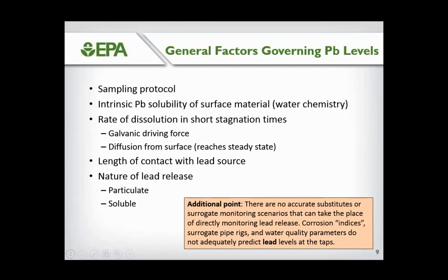So things like the galvanic driving force or the rate of diffusion from the surface are critical. The length of contact with the lead surface and the nature of the lead release. Is it particulate with these high percentage but small particles, or soluble lead?